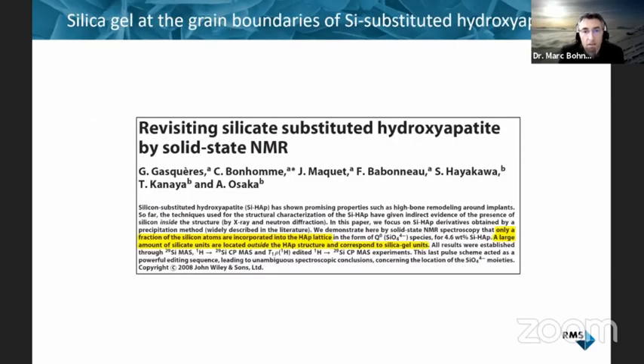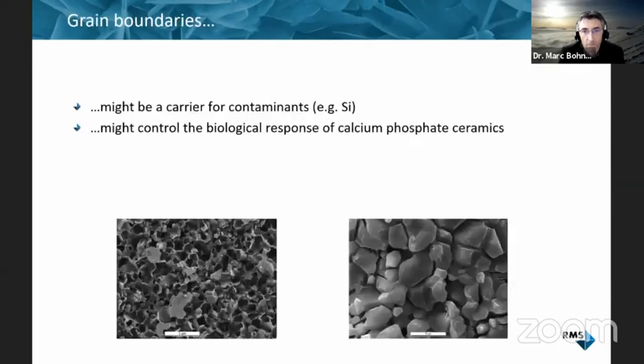One potential hypothesis is that the silicates are not present only in the lattice of the hydroxyapatite, but also at the grain boundary. And this group from Paris and Japan showed that actually there are some silica gel units that are present in this silicon-substituted hydroxyapatite. And so the silicon or the silica might be released by dissolution of the grain boundary. And in fact, the grain boundary composition is a very big topic in ceramics. It has not been really addressed in the field of bioceramics.